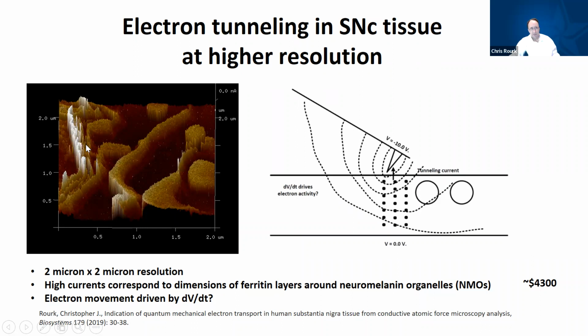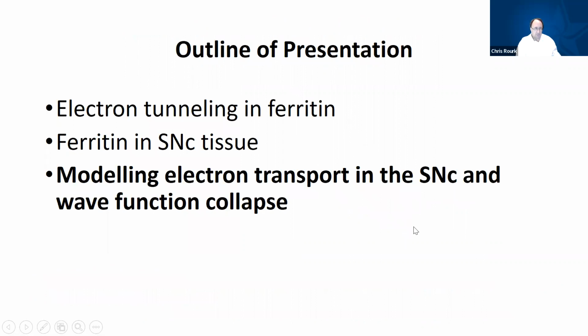It changed over time: a very short period of time when the probe started to touch the surface, then during the entire period when it was in contact at the peak, and then there's a third measurement taken over the entire oscillation period, which was much less. So with this evidence of electron transport in SNC tissue, the question follows of, is there electron wave function collapse occurring, and to what extent? And this could be modeled and potentially measured too.